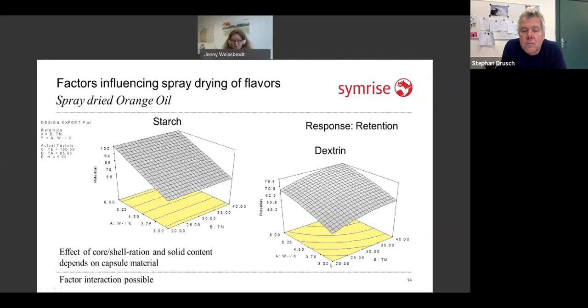For the dextrin, of course, the solid content is important. Even here, it is important. And the ratio of your active to wall material too, which means just have as much material as possible to entrap your material and then have a high solid content. And then you have a chance to have a fairly good result, even for this not emulsifying carrier material.